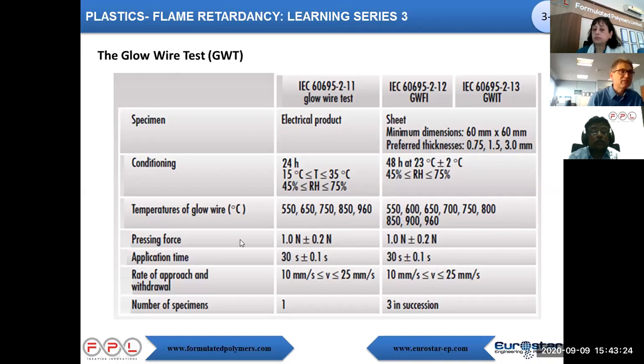The pressing force is 1 Newton. It's design related. You cannot avoid it. And the application flame time is 30 seconds. The rate of approach and withdrawal of the wire is important, especially for GWIT, the ignition temperature, because if you have a shock or if you are going too fast or too slow, you can change the measurement. This is why modern apparatus are now automated. You don't have control on this one.